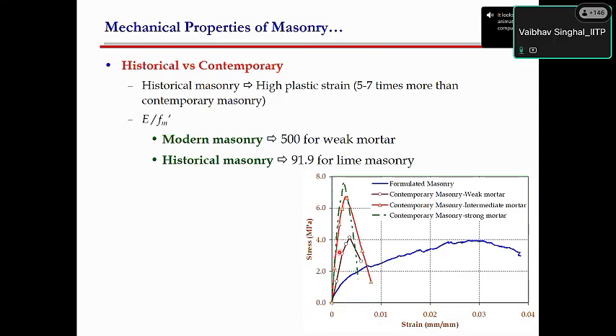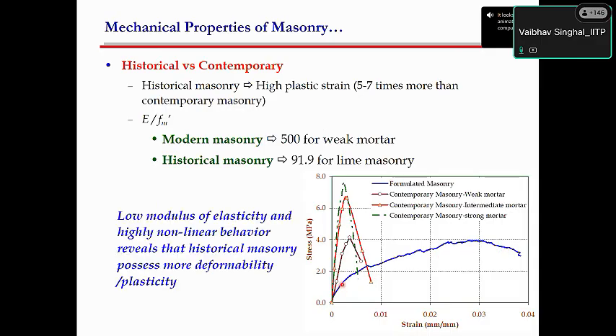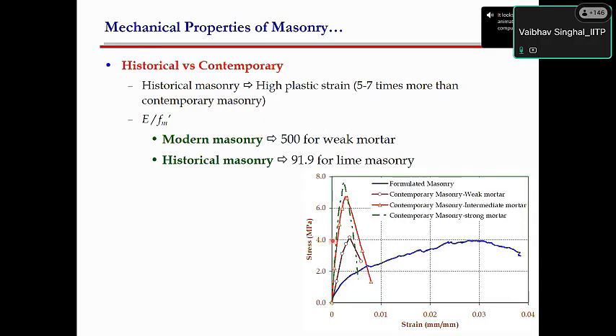And then we also compared the results with our traditional or contemporary masonry. You can see the blue line is the historical masonry. The historical masonry response is quite soft, which also shows that it is quite flexible. Whereas the conventional masonry, even the weaker one, has a significantly higher elastic modulus compared to the historical masonry. So one can say this could be a reason why these older masonry structures are still standing. They have not experienced much damage in the last 1,000 years, or 300 years, or 500 years. Low modulus of elasticity and higher nonlinearity reveal that historical masonry has more deformation and more plastic capacity.